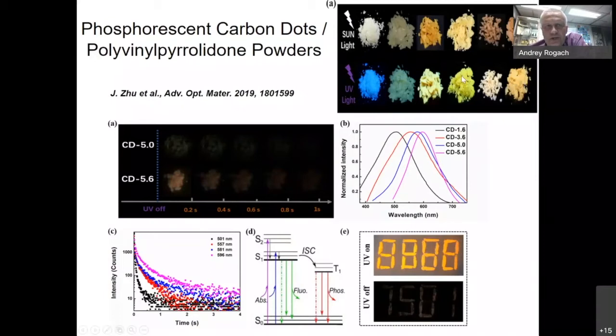But this emission is so-called phosphorescence. Phosphorescence is different from photoluminescence because phosphorescence is a delayed emission. So we illuminate them by UV light and then we switch UV light off. And even after hundreds of milliseconds or up to 1 second, these powders will still keep emission. We call it phosphorescence. And this can be very useful because it can have some applications in encoding information.